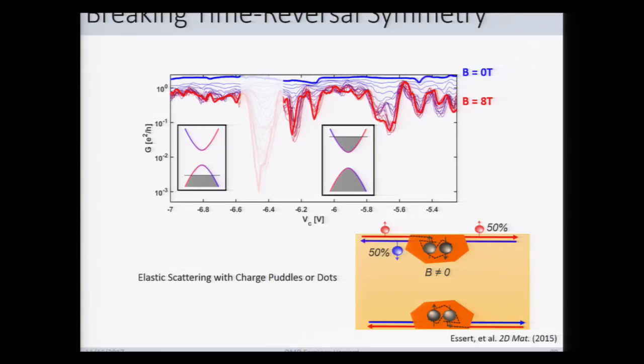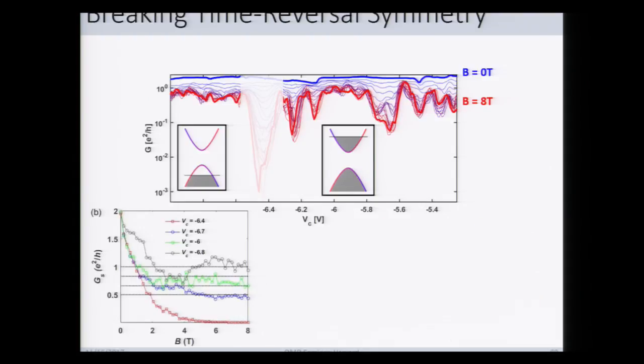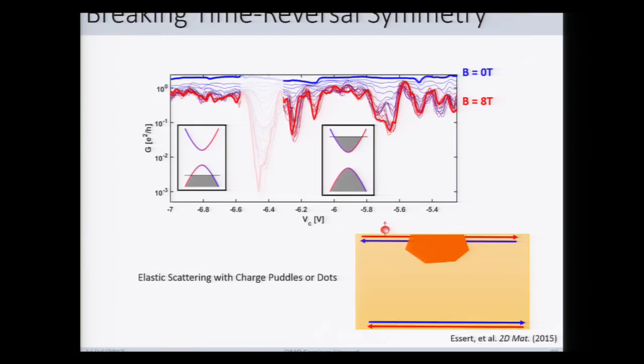With a few of these dots causing backscattering along the edge on either side, we can get this small reduction of conductivity that's not exponential in the magnetic field. And indeed, they do predict exactly this sort of shape where it drops very quickly initially and then saturates.